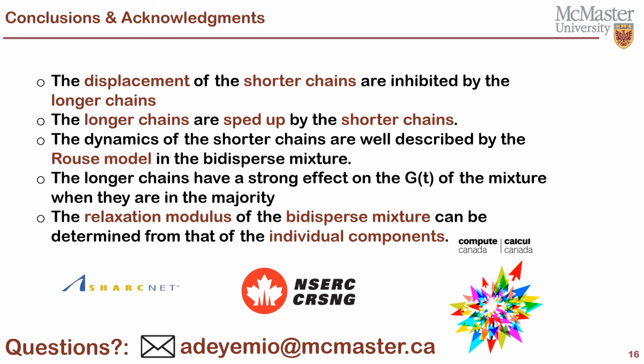In conclusion, by using a simplified molecular model to represent our bidispersed systems, we have shown that the displacement of the shorter chains are inhibited by the longer chains, while the longer chains are sped up by the shorter chains. We have also shown that the shorter the chains, the more the displacement for the longer chains. Also, we have shown that for both monodispersed components and bidispersed mixtures, the Rouse model still describes the relaxation of the shorter chains, while we see that the stretched exponential can be used in describing the relaxation of the longer chains.